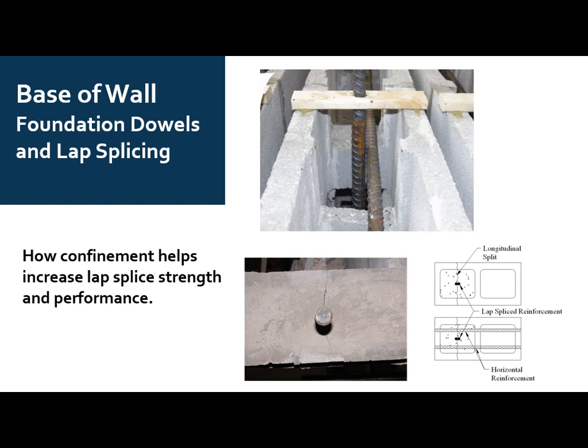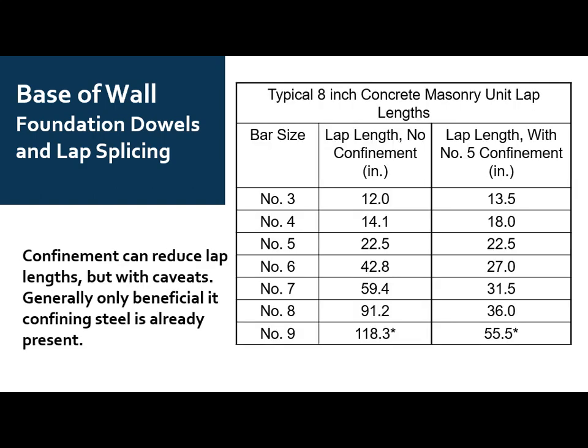What you see here on the bottom photo is actually looking directly down the axis of a lapped bar. So this is the end of a lapped bar, and you can see these cracks just starting to form. This was a test specimen at impending failure, showing the mechanism that develops this longitudinal split. So long and short, with our confinement factor, we can add steel in. It can reduce our lap lengths, but as we'll talk about, there are pros and cons and a big caveat on where and how you want to actually use those details.